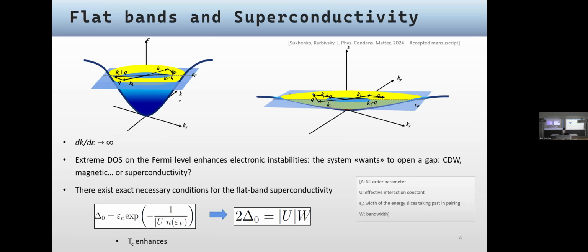And now to the question of the flat bands. It was one of the features that initially, when nothing was clear about the LK99 story, was considered a point of interest. Theorists also delved into it at first. So when the flat bands cross the Fermi level, the density of states diverges. It's very huge at that level, and it means that from the energy point of view, the system wants to open a gap, basically to lower its energy collectively, and in a way to organize into some next quantum state. It can be superconductivity, charge density wave, or some other order.